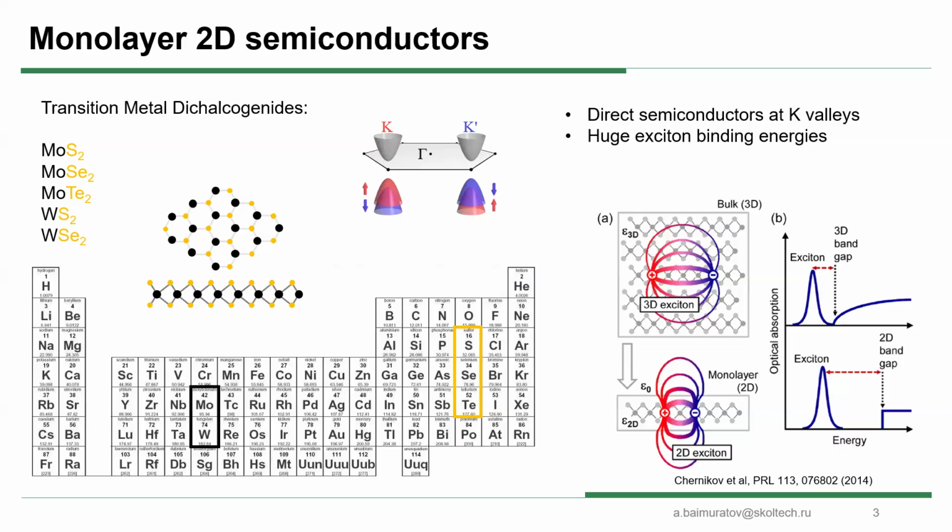That is also because now most of them are encapsulated and this screens the interaction a lot, while previously if you were freestanding, or at least on top of a substrate, it was larger. So maybe it's partially that, but I believe if you screen, you have two effects probably: one increasing the band gap and one changing the binding energy. Usually we compensate a bit, but in any case, now I believe it's 100 or 200 meV.